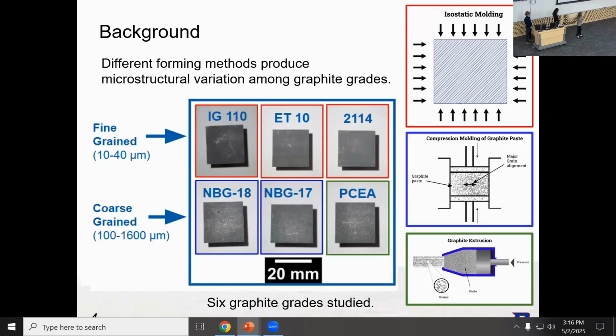Then on the bottom row, we see grades NBG-18 and NBG-17, which were formed by a technique called vibrational molding. This is similar to the image shown there of compression molding with uniaxial pressure applied on 2 faces of the graphite, with the only difference being the base is vibrated to increase the packing efficiency. And then the final grade was PCEA, which is formed by extruding graphite paste out of a specific shape. Now, these bottom 3 resulted in relatively coarse grain graphite between 100 and 1600 micron grain diameter.